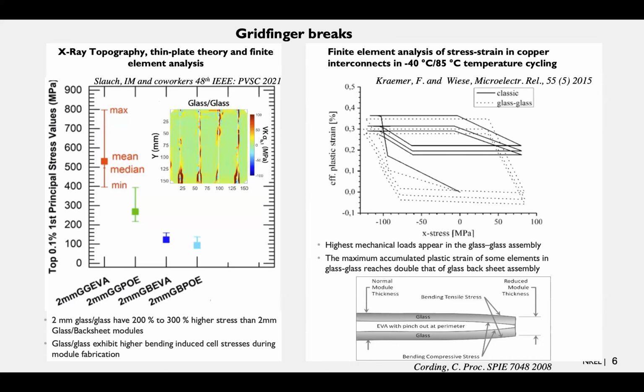Yeah, and I might add that the whole reason we initiated this combined accelerated stress testing was exactly for the premise of the question. We were seeing all kinds of failures in the field which the IEC 61215 based or extended tests were not finding, such as polyamide failures, PVDF failures, PID, LETID. All of these things were more or less found after the module shipped, and it's only years later that we got around to develop mode-specific tests for them. This kind of frustration is what led to the development of combined accelerated stress testing. I think we have a lot to learn about what it's telling us and how that relates to the field, and that's a rich topic for continued research.